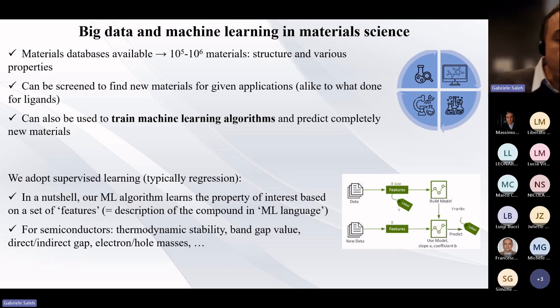The properties we are interested in for semiconductors are the thermodynamic stability, the value of the band gap, and whether the band gap is direct or indirect, because this influences whether it can efficiently emit light, and the masses of electron and hole, and there are a bunch of other properties. In this talk, I will focus mostly on thermodynamic stability, which is the most important property, because if a material is not thermodynamically stable, it cannot exist.